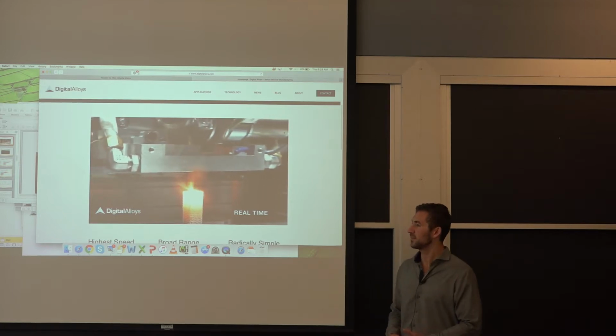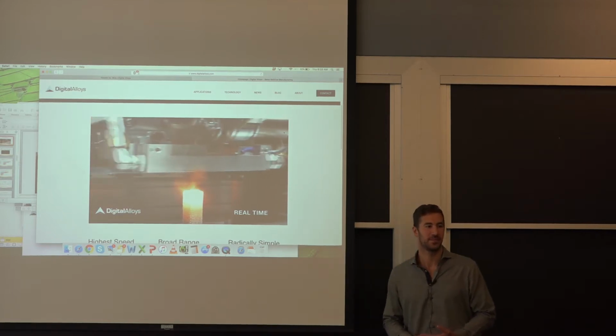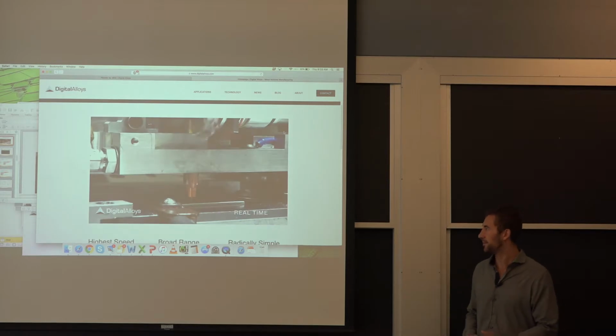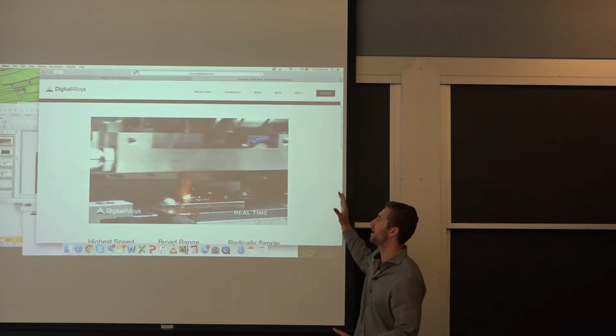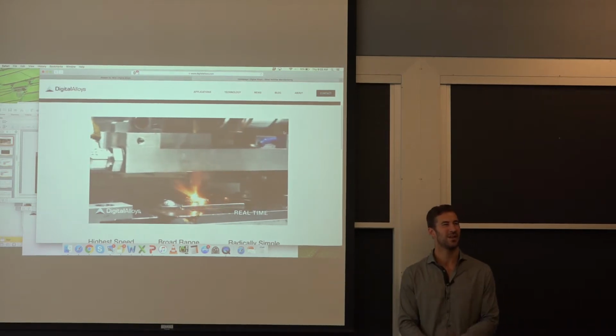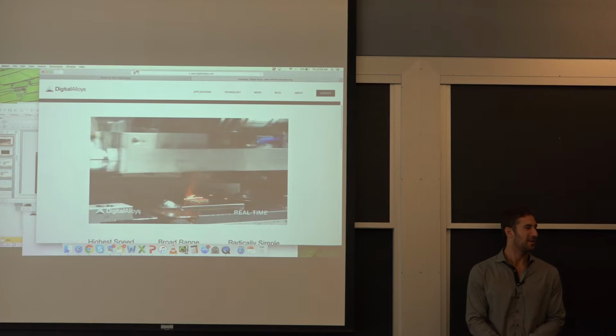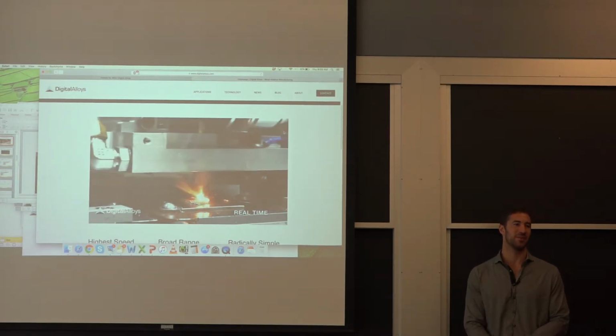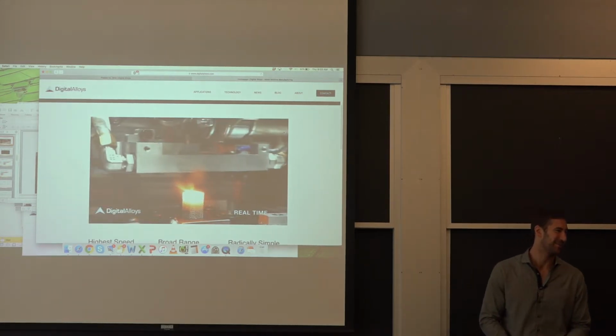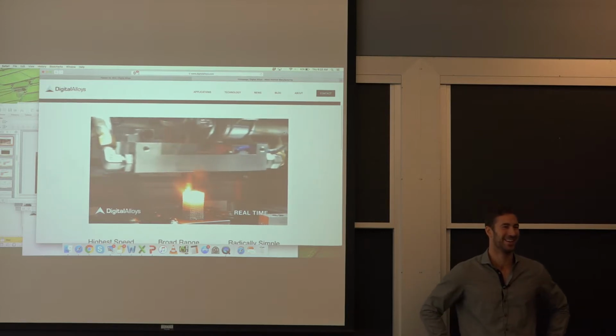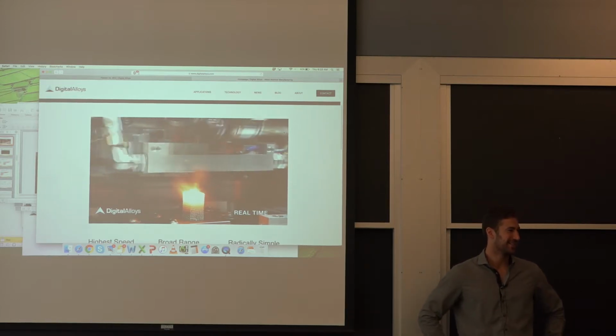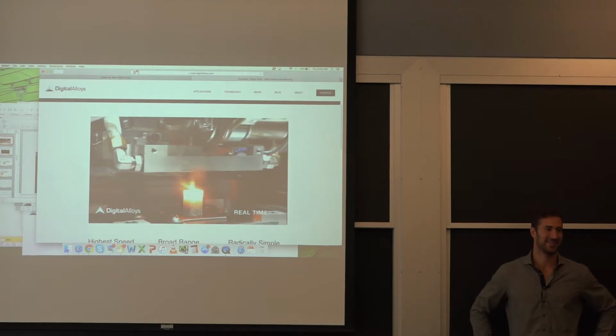I'm curious, is this actually a titanium part that you're printing right now, or is this some other material? Yeah, this is titanium. Is this done in an oxygen-free environment, or in the atmosphere? What you don't see is the bigger printer behind this. This is in argon. We have a chamber and we purge it with argon. Would it be on fire? It would be heavily oxidized. You'd lose a lot of strength in the material. It would look funky colors. I don't know if it would catch on fire, but it could, maybe, if there's some oxygen in there. If it was powder, you could start a flare in there and burn the whole glove box down.